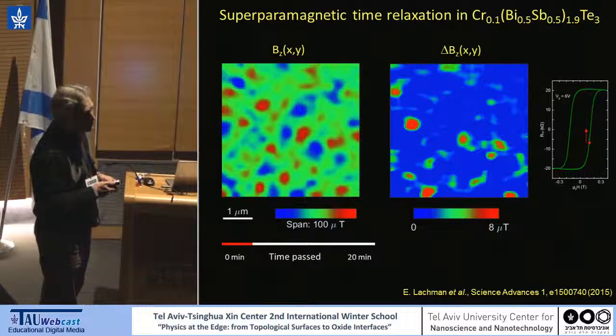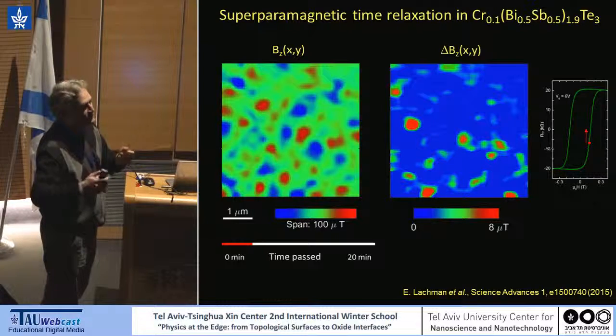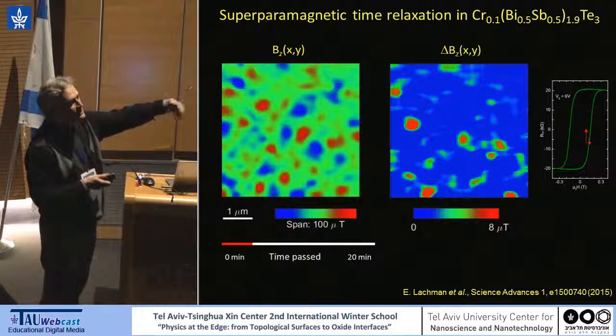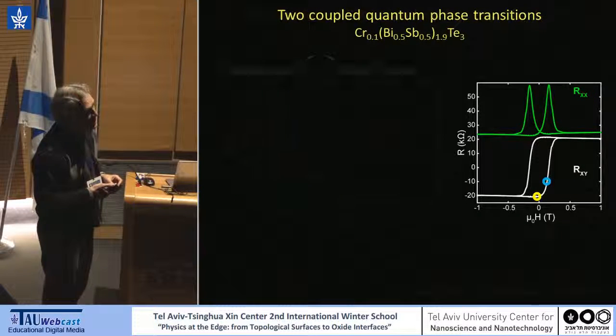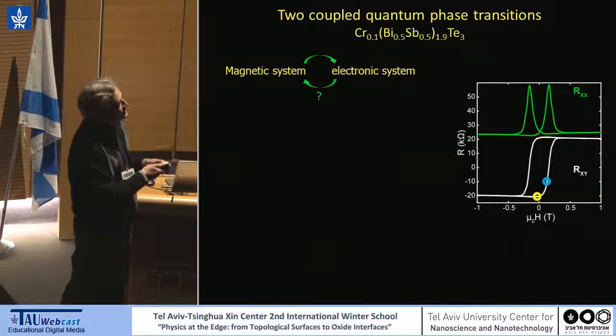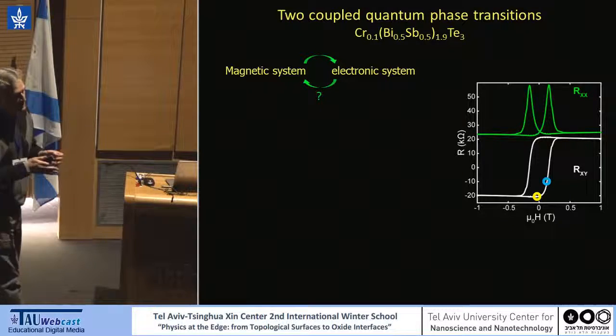Yes. But the electrons feel the sum of both fields, right? Yes, but the exchange is much larger than the applied magnetic field. So the applied magnetic field for electrons at these fields, this is 0.1 Tesla. So this is negligible. What's the estimate for the exchange? Exchange energy. For the exchange coupling. Yes, I cannot tell you numbers, but you can see it here. So we are not fully quantized, and as you can see, it is flat. So the external magnetic field does essentially nothing. Okay, does it answer your question? Yeah. Okay.